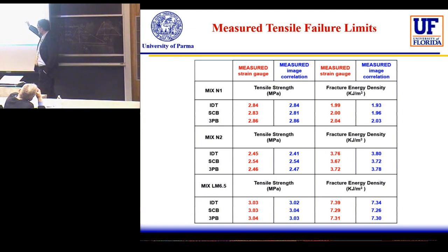A few megapascals of difference in the configuration. But the fracture energy is more consistent as a parameter, constant for the material. So we can see that we are more or less at the same level for each material, and the difference among the different materials is strongly consistent. So the results in terms of IDT allow us to say that they are different, but not by much. Big is the difference between, in particular, the highly modified bitumen and the natural one.